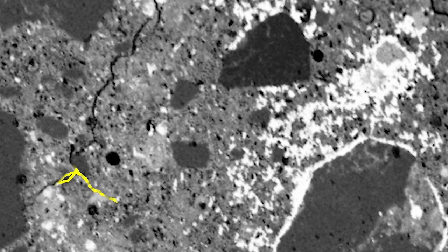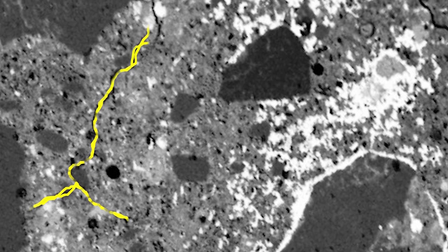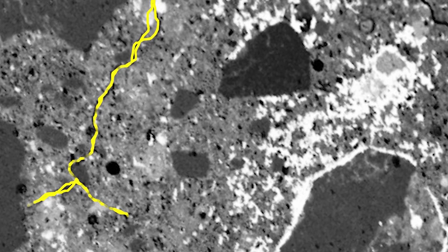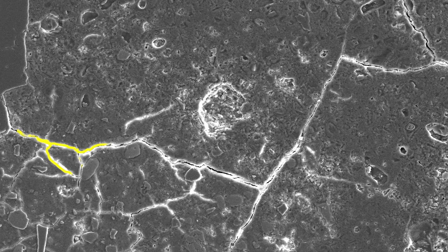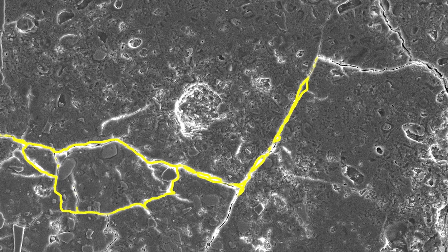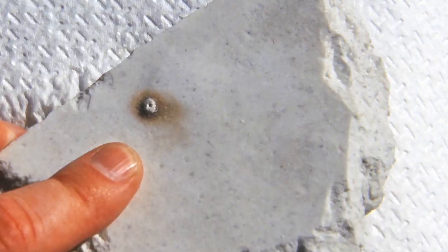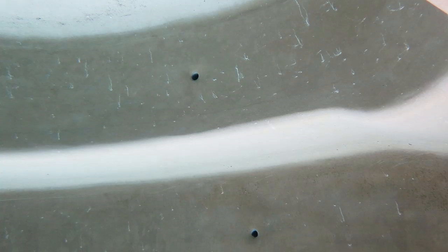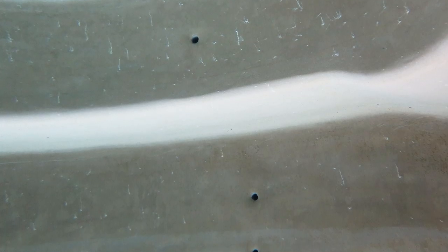However, about every 2 to 4 inches, larger shrinkage micro cracks typically develop. These micro cracks are much wider, typically about 5 to 10 microns in width, and these generally take several days to several weeks to fill shut with cement hydration compounds. During this time, any aggressive water — such as low calcium, low carbonate alkalinity, or low pH — can attack these larger micro cracks that haven't fully sealed shut. This scenario can allow for the second type of nodule problem to occur, where hundreds of small calcium carbonate growths can occur on areas across the finish where open micro cracks exist.